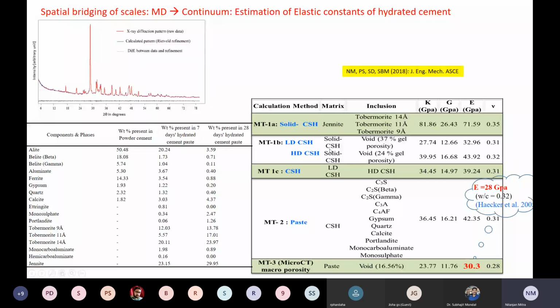Eventually, we perform elastic constants for all of these individual things, and we come up with a value of your elastic constant of something like 30.3 gigapascals. And if you do an ultrasonic type of test, which is basically an experimental investigation in order to find out the elastic modulus, that's what is done for any material for that matter, you get something like 28 GPa. So I think we can safely say that the methodology that we are prescribing is quite matching with what you're obtaining from that experiment.